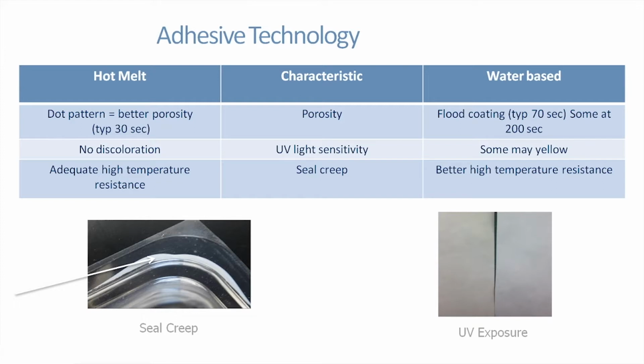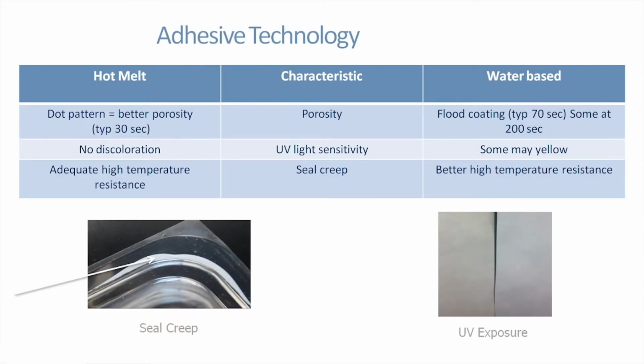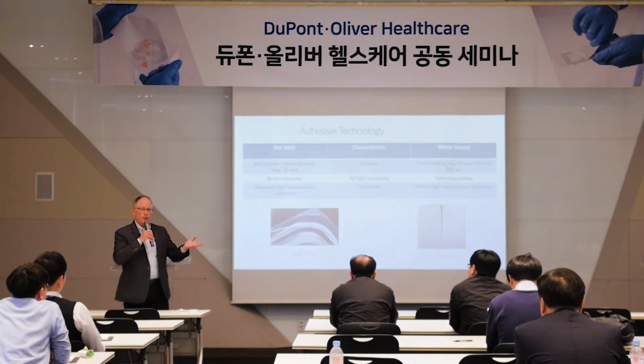And then the last one before the translation, the seal creep, is a scenario related to the strength of the adhesive at higher temperature. During EO sterilization, it's elevated temperature. During transportation in a warm climate, it's elevated temperature. Adhesives, almost all of them, are going to get a little bit weaker when they're warmer. So some of the water-based coatings in our portfolio have really, really good strength at high temperatures during EO, so they're very creep resistant, meaning creep to open.